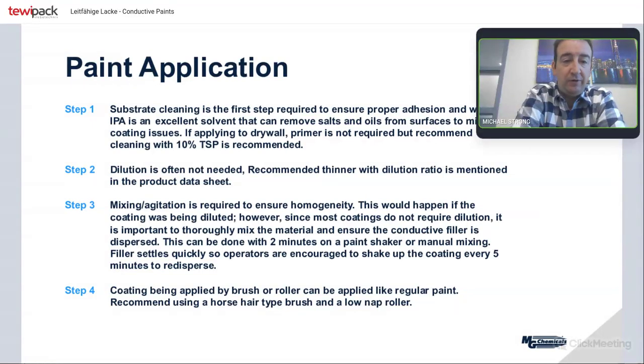Now, mixing agitation required to ensure homogeneity. This is very important because the conductive fillers that we use are very dense relative to the rest of the paint system. And what happens over time is that they will tend to settle out into the bottom of the coating system. So we need to introduce constant agitation to make sure that our mixture is completely homogeneous and to make sure that the coating that we are spraying has enough conductive filler to do its job. And then finally, any coating that's being applied by brush or roller, apply it like it's a regular paint. We suggest a horsehair paintbrush, which is similar to any paintbrush you would commonly use applying other paints. If you are rolling it onto a surface, just use a low nap roller.